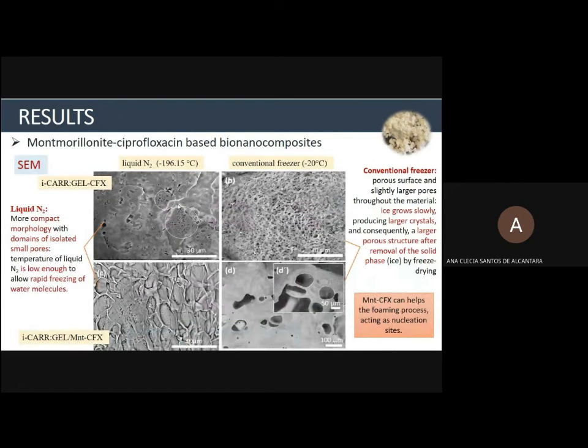The surface of these bionanocomposite materials was also observed by scanning electron microscopy. In the case of the beads prepared by liquid nitrogen, a more compact morphology with domains of isolated small pores is observed. In contrast, with conventional freezing, a porous surface and slightly larger pores throughout the material are observed.